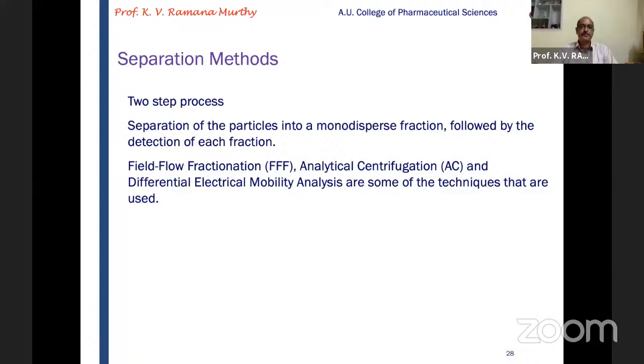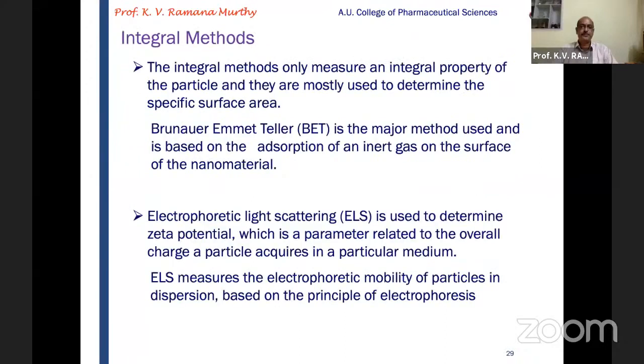Integral methods are used only for measurement of the integral property of the particle. We use the BET adsorption isotherms for evaluating the nanomaterials. And we also use the electrophoretic light scattering technique for determining the zeta potential, which is a parameter related to the overall charge of a particle in a particular medium, and it also correlates with the stability of these nanoparticles.